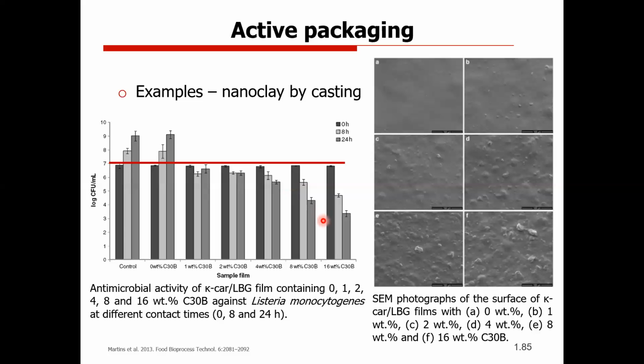So we see here that we have an antimicrobial active film with nanoclay, but in this case, with nanoclay you have to be careful because it should not migrate to foods. It is allowed in some plastics, but we have to guarantee that there is no kind of migration. But it's very interesting to have this material that has the two possibilities of reinforcing and improving the barrier properties, as I showed before, but also having this active capability to kill some bacteria like Listeria. That is a huge problem in the food industry.